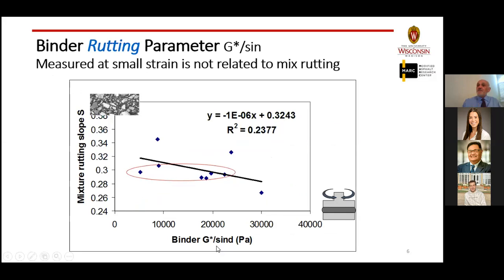Same temperatures, same aggregate structure, if you will. So it's the same mix design, but we just changed the binder. Look at this data set here. You can be anywhere between 6,000 pascals, or 6 kPa, up to 24 kPa, yet your mixture behavior is approximately the same creep slope. And people said, well, this is because the aggregate structure really dominates the rutting. The fact is, this is not the case.